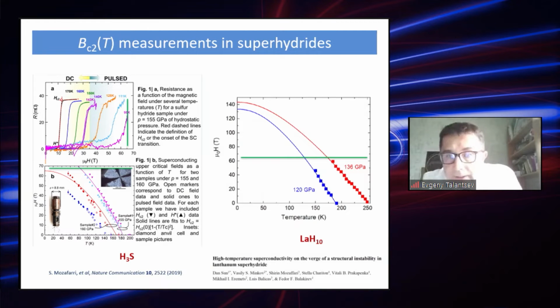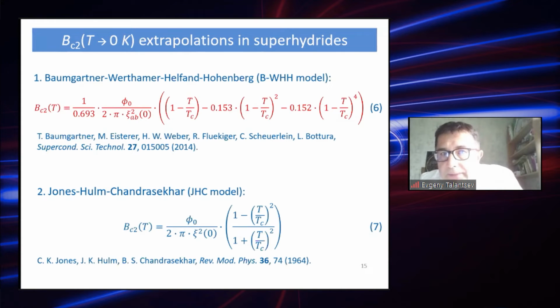So we can use a similar story for all other hydrogen-rich medium temperature superconductors. A very high magnetic field is required to suppress superconductivity in them. So we can use some extrapolative model to extrapolate the value at ground state, and the most popular at the moment is an analytical approximation given by Baumgartner et al. for the classical WHH model. So we will use that.